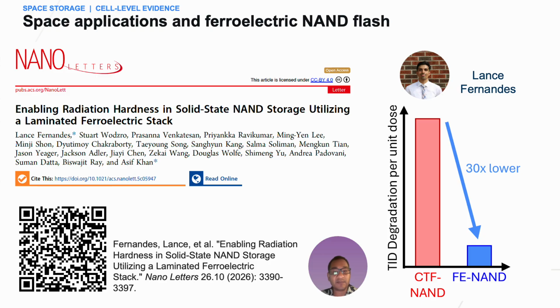The paper describes the device design, irradiation protocol, stored charge, retention, programming, and disturb result behind that comparison. The 30 times comparison is based on normalized threshold degradation per unit dose, so it compares the sensitivity rather than two tests performed at two different doses. The contrast between the charge trap benchmark and ferroelectric NAND devices, as we observed in this work, is large enough to establish a compelling mechanism-level advantage of ferroelectric NAND for radiation-tolerant storage applications.